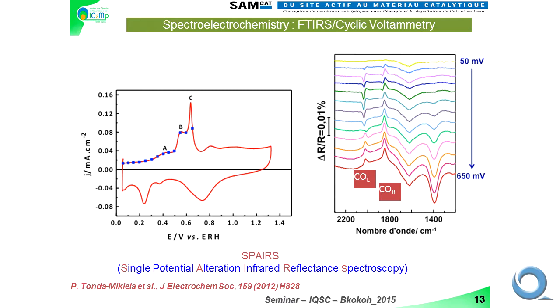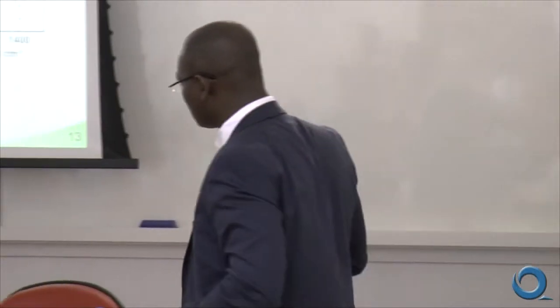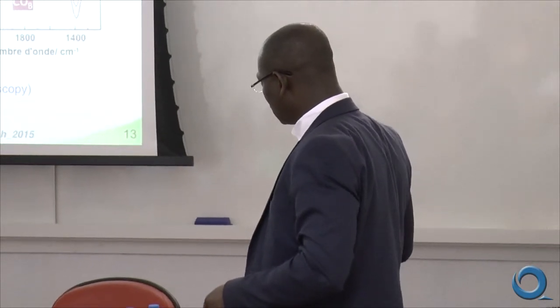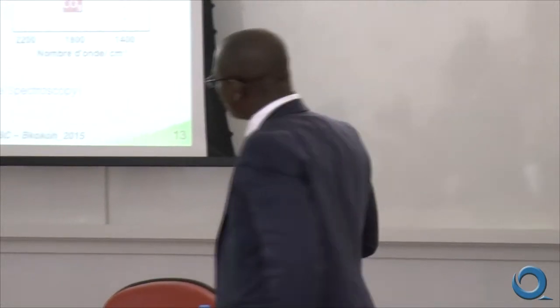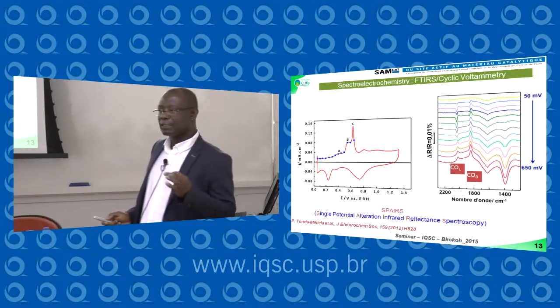So at 0.1, for example, you adsorb CO at the surface of your catalyst, and when you reach the double layer, you stop and you record your voltammogram. For example, you have the oxidation of CO, we discussed about it, and after you recover your surface, and you can continue. At the same time we record, by this technique, spectra. This means that we scan the surface of the catalyst and at the same time we record CO stripping. By the way, during this interval we record and we have two kinds of CO at the surface.